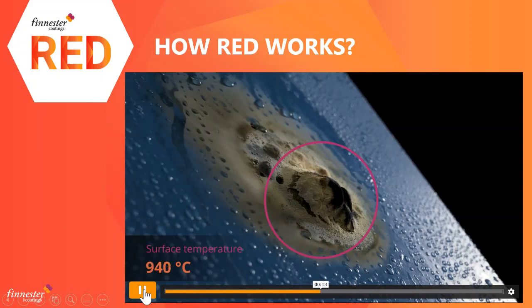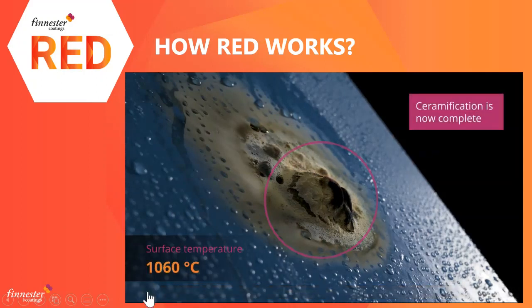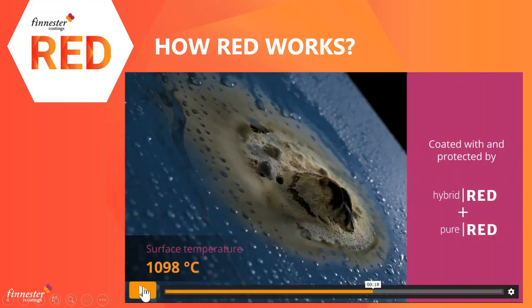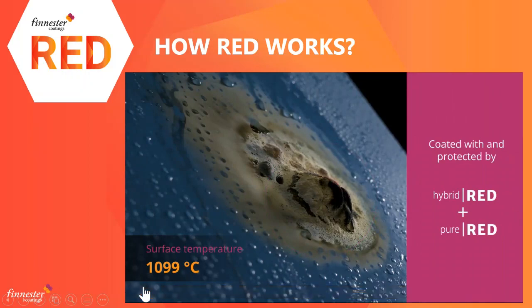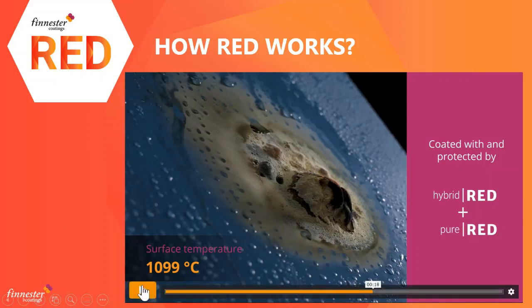And even when you keep burning it, even at those temperatures above 1000, you can see it just goes red hot, and it's stable. It's stabilized in those temperatures, and you can burn it for a longer period of time. So this is the 2-coat system on the standard composite.